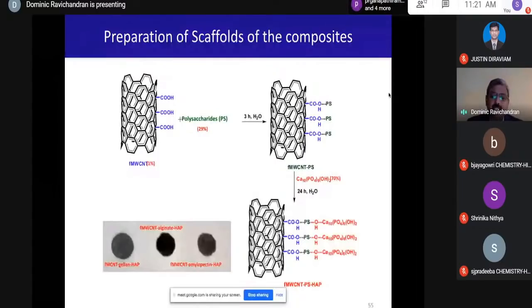And in this case, we freeze the suspension at minus 80 degrees in a particular mold so that it solidifies, and then it is lyophilized and dried so as to get the composite scaffolds. The composite scaffolds prepared are shown in the photograph. You can see how it looked.